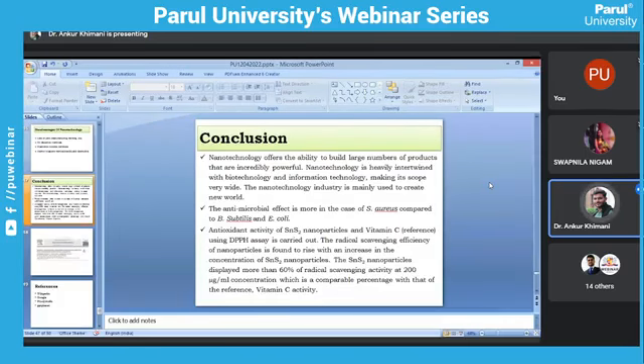The antioxidant activity of the SnS2 nanoparticle and vitamin C reference using DPPH assay is carried out. The radical scavenging efficiency of the nanoparticle is found to rise with the increase in the concentration of the SnS2 nanoparticle. The SnS2 nanoparticle displays more than 60% radical scavenging activity at 200 microgram per ml concentration, which is a comparable percentage with that of the reference vitamin C activity.